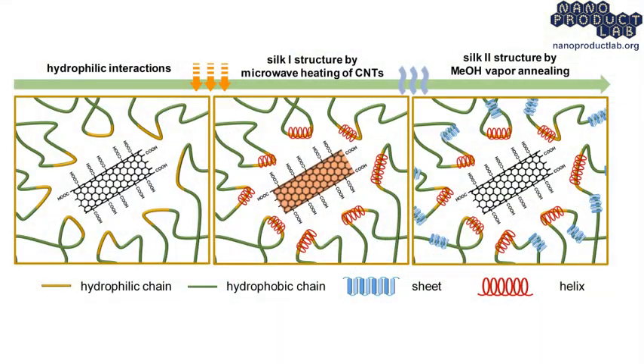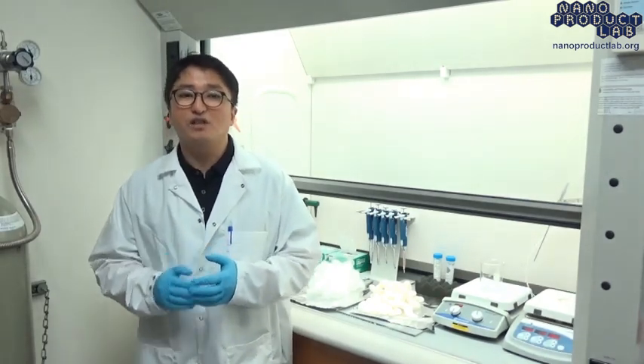We added surface functionalized carbon nanotubes into silk fibroin solution during the regeneration process. And after preparation of the composite film, we used microwave irradiation for the local heating of silk molecules nearby CNT using the differences of electroconductivity between the CNT and silk fibroin. And we confirmed that the local heating of silk molecules resulted in local crystallization. So we further investigated the effects of local crystallization on the material properties of regenerated silk composite films.